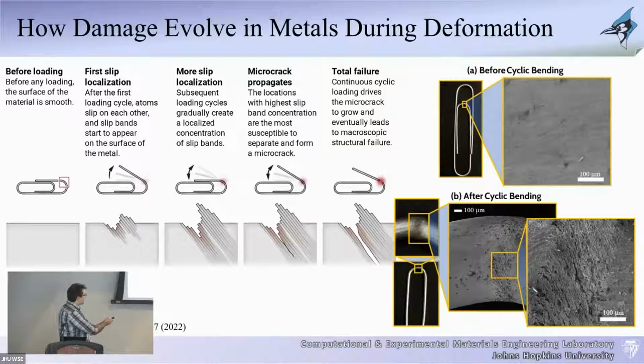He has a paper clip. He bent the inner portion here and eventually led to fracture. But before it led to fracture, he took it inside the SEM before he did the bending experiment, and actually after he did the bending experiments, and you can see that transition from the smooth, pristine type of surface to a very rough surface. And you can see from zooming in all these types of cracks that are forming. These are the precursors that eventually lead to this larger crack that propagates and leads to failure.